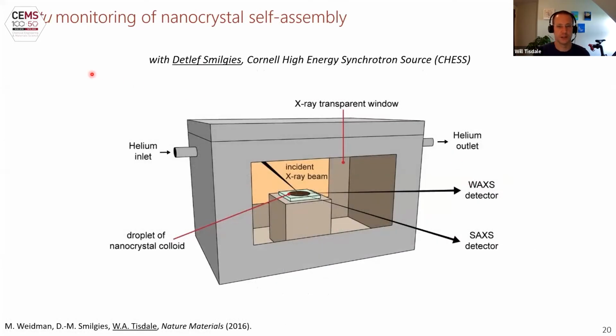We got very interested in how these superlattices form. And so my student Mark was going up to CHESS, the Cornell High Energy Synchrotron Source, at the time. He happened to be going on one trip at the same time that Detlef Smilgies, a staff scientist there, had just finished fabricating a chamber for in situ X-ray scattering experiments. It's a chamber that you can close up, and it has Kapton windows that are transparent to the X-rays, but can enclose a chemical environment inside the chamber. And so you can understand in situ processes that are going on.